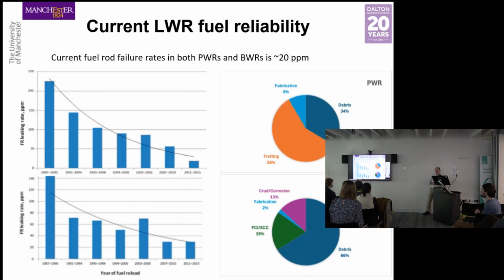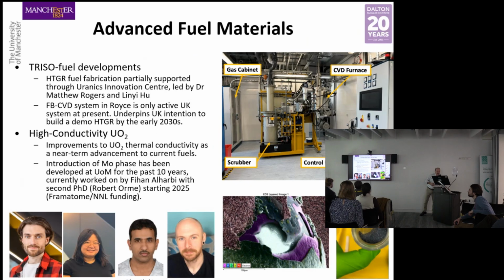Generally, it's pretty reliable. Current failure rates are down at about 20 parts per million, roughly of the order of 10 to the minus 5. So it's pretty good, but it's not perfect. Anyway, this is what we're doing to make things better in the last 2 or 3 minutes that we've got available before the fire alarm sends us on our way.